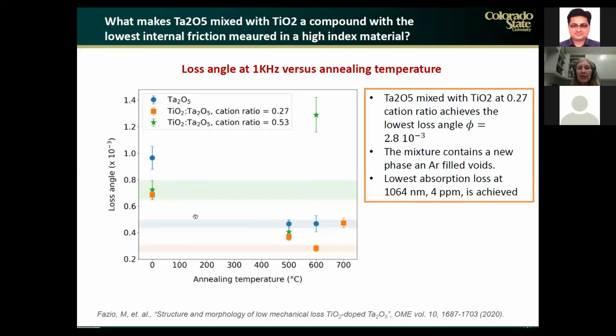But when we start increasing the temperature, we see that at about 500 degrees C, that is when we observe the crystallization of the higher content titanium sample, then the loss angle jumps significantly. And again, we typically see this increase when crystallization starts. But the lower value of mechanical loss, which is shown here, is obtained in the sample that has a cation ratio of 0.27.